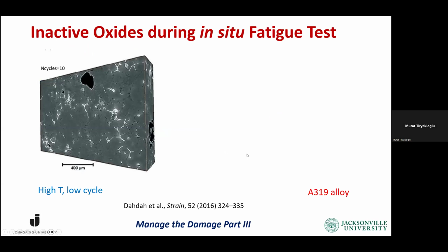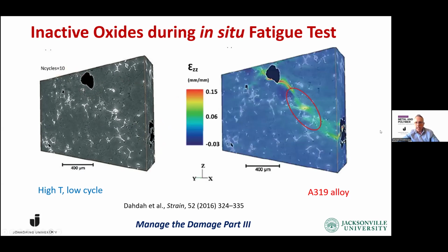With the emergence of new technology showing us in situ testing, all of this thinking is now being challenged. So I'm going to show you a few examples that we saw in the literature before turning it to Tony. These are inactive oxides or the hidden damage during in situ fatigue testing. Here's an example of 319 alloy. We can see two pores here, one pore on the right-hand side, and there's another one here. And we're at the 10th fatigue cycle. By the strain fields, you can see that there is a field between them, and there's one that at least opened up almost at the midpoint between the two pores.